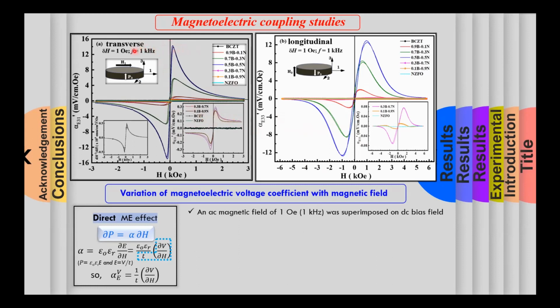The maximum response observed in the transverse mode was higher than in the longitudinal mode, though the difference was small. And secondly, the maximum response in the transverse mode was obtained at lower magnetic field values, I think around 100 to 200 oersted. Whereas in the longitudinal mode, the maximum in the magnetoelectric response was observed at a higher field, around 450 to 1000 oersted. This difference is basically due to the large demagnetization field, which is found in the longitudinal mode.